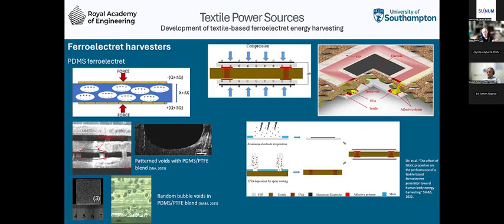But one thing that did make it very difficult is that this structure relies on a bonding step. And if you add PTFE, you alter the surface energy of the PDMS, which makes this bonding process very difficult. So our final version of this was to go for a process where we deliberately induced bubbles within the formation of the PDMS PTFE blend. These bubbles then act as the voids, and we achieve that ferroelectret type performance. That shows you one with this ferroelectret process with a soft, flexible material.